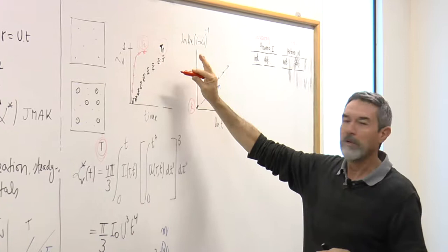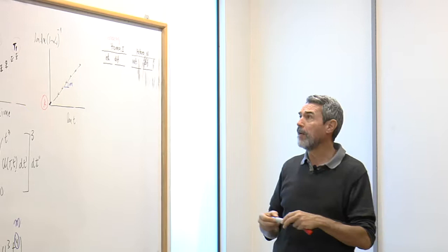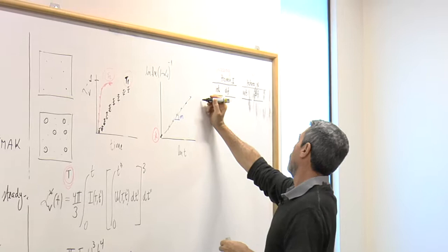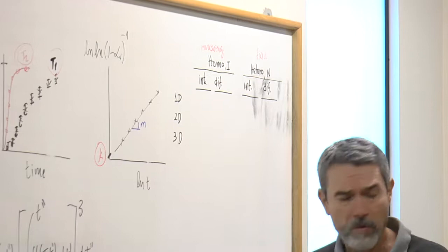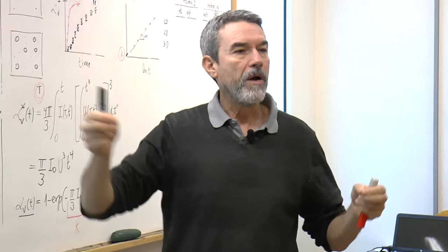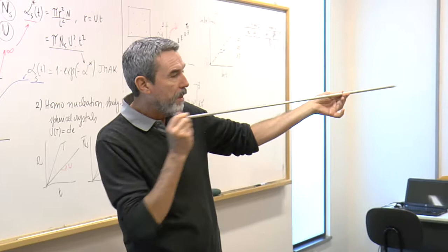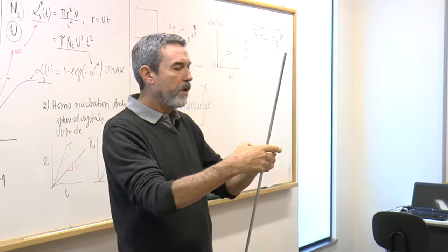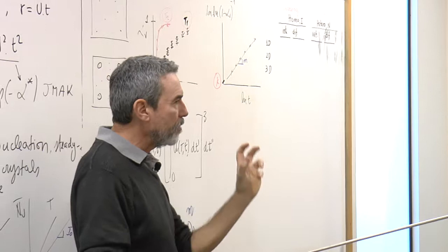Isothermal treatments produce this plot. From the plot, we can calculate M and then compare with the theoretical values of M. The theoretical values of M can be seen for one-dimensional growth, two-dimensional, and three-dimensional. By one-dimensional growth, I mean acicular, rod-shaped particles. There are some crystals, like wollastonite or mullite crystals, that grow almost unidirectionally, rod-shaped. Or you can have plates or disks. This is two-dimensional growth. Or cubes or stars or spheres, three-dimensional growth. This is the shape of the crystals that grow.